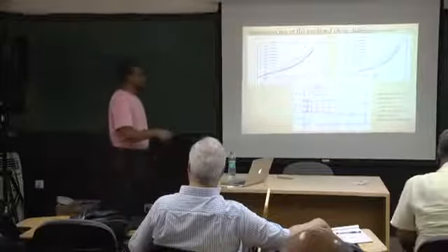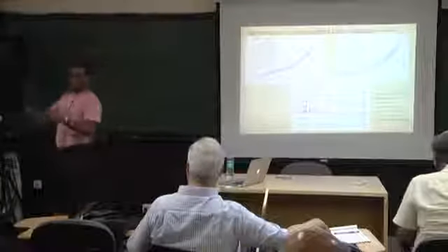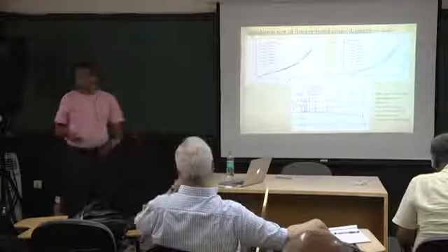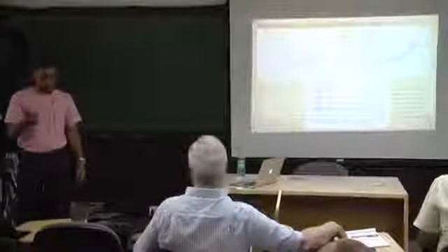One point I told you: if you have a system with constraint and without constraint, in the two cases the constrained system should have less configurational entropy. That is the thermodynamic constraint that you cannot violate. But then people will say that if you keep adding constraints, you should actually freeze your dynamics, so this is thermodynamically not consistent. But you can actually show that it is still thermodynamically consistent. There is nothing which stops you from having this picture where the divergence temperature does not change with pinning, but the fragility changes.